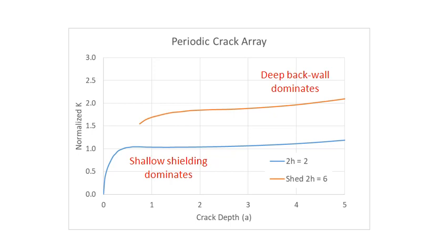a bad situation. Obviously, that depends on a lot of factors, including the nominal wall thickness of the pipe wall and the crack spacing and how much stress we've got going on. But the key lesson is that for shallow cracks, that shielding factor will dominate, and it's not until you get deeper that you start to lose stability. So that gives you some understanding of why a lot of stress corrosion cracks will grow so slowly and go dormant.